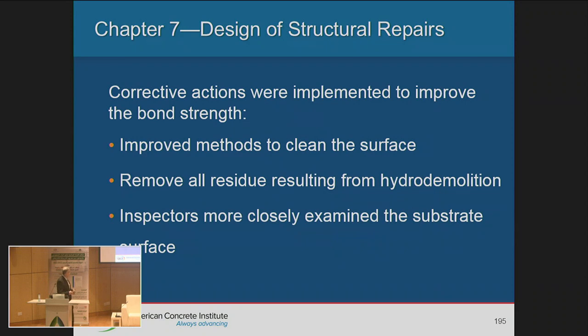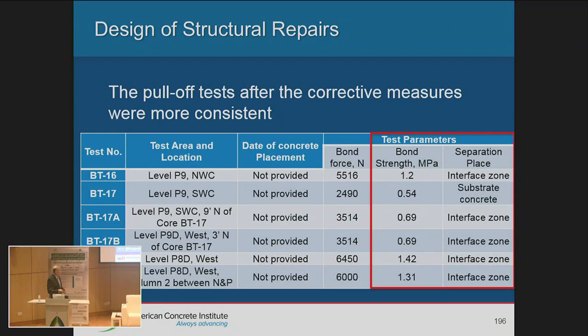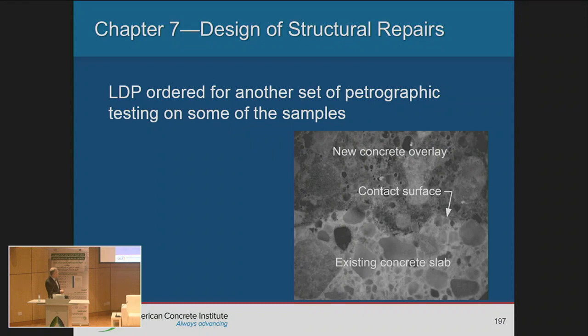So they added more inspectors to closely examine the work of the construction. They continued and did some more tests after a while, and found that the test results increased, and the engineer was happy with those test results. Because here, when we have the low, it was in the substrate. It wasn't really at the interface. So the engineer was happy with the test results, and the project continued. They took samples here where you had low results. And they found from the petrographer that there is very good bondage and there is no debris between the existing and the new material.